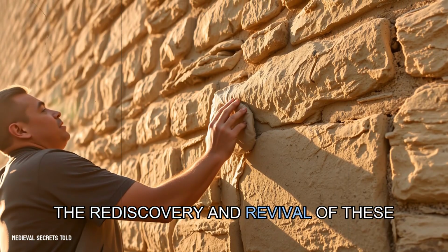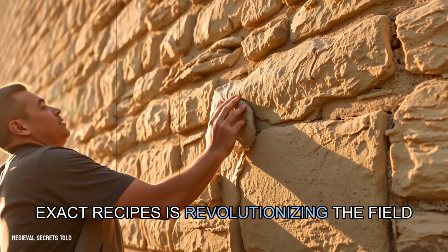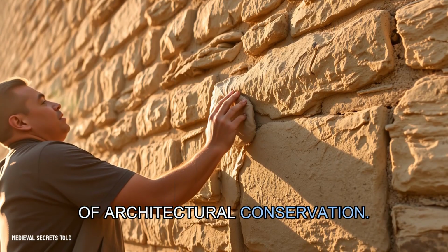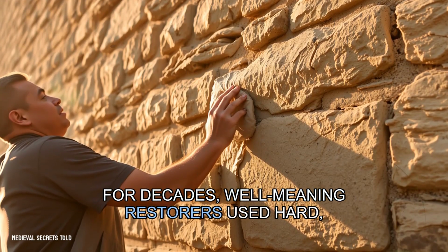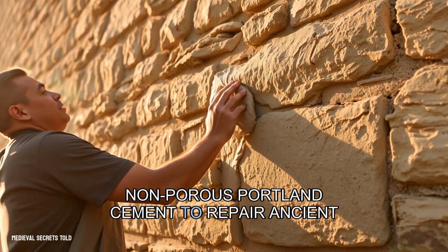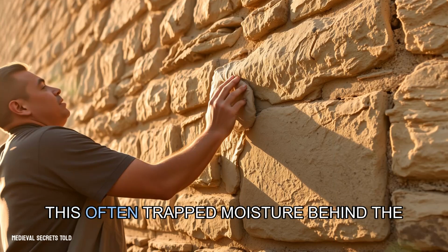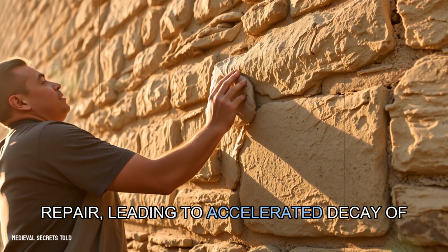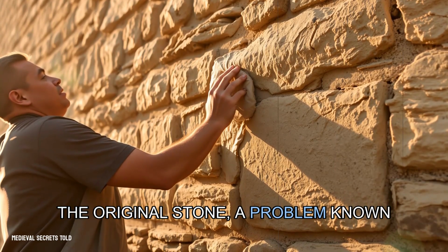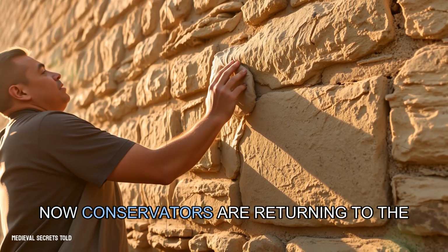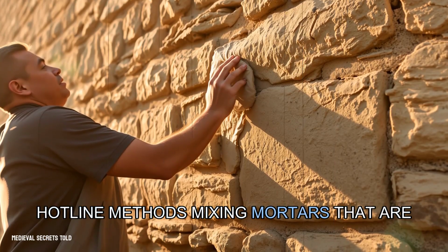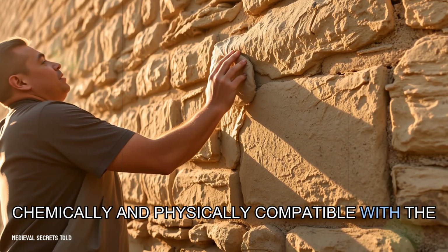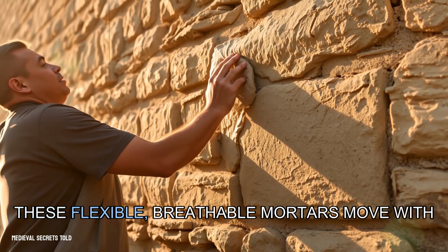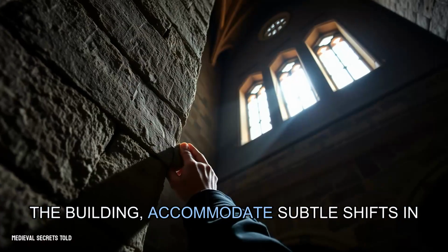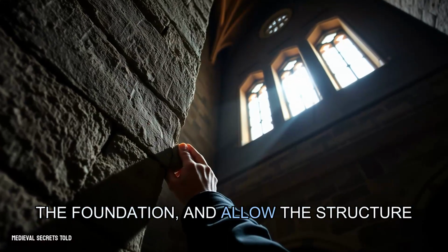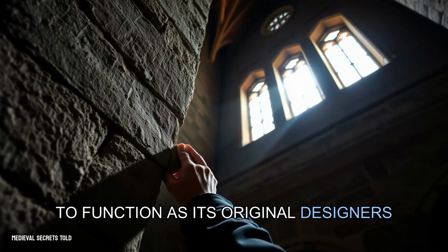The rediscovery and revival of these exact recipes is revolutionizing the field of architectural conservation. For decades, well-meaning restorers used hard, non-porous Portland cement to repair ancient buildings. This often trapped moisture behind the repair, leading to accelerated decay of the original stone, a problem known as hard capping. Now, conservators are returning to the hot lime methods, mixing mortars that are chemically and physically compatible with the historic fabric. These flexible, breathable mortars move with the building, accommodate subtle shifts in the foundation, and allow the structure to function as its original designers intended.